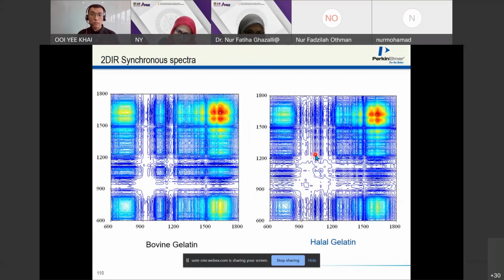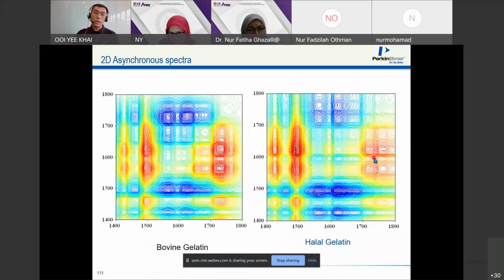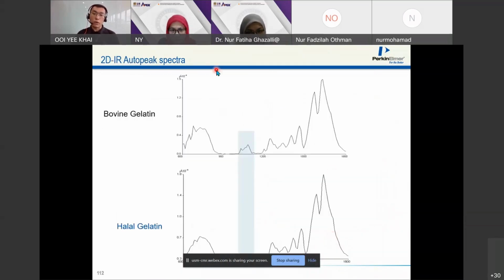Based on the synchronous plot, it shows the similarity between the bovine gelatin and the halal gelatin. You can see that the more intense the color, the more changes occur at this particular wave number. It has a similar region, meaning highly similar. Even the asynchronous plot shows it to be quite similar in the regions of interest. For the bovine and halal, we can then conclude that the bovine gelatin can be used as a replacement for the halal gelatin. You can generate a spectrum for each of the points that you see here. So this is what we call 2D.